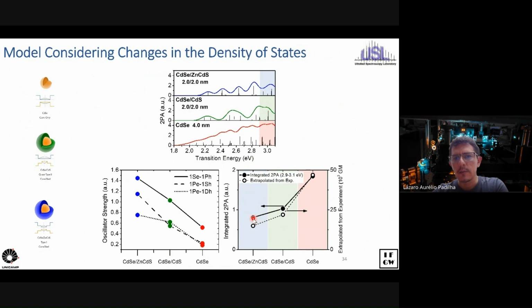And so here the full dots are the numbers that come out from this integration under the simulation. And here the open circles come from the experimental data. So you see very good agreement, indicating that what we're seeing actually comes from the changes in how the density of states changes in different types of binary structure.